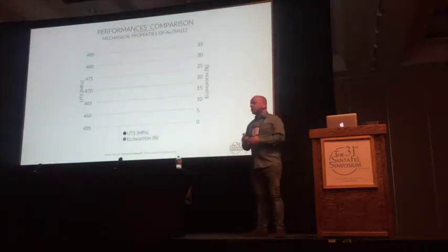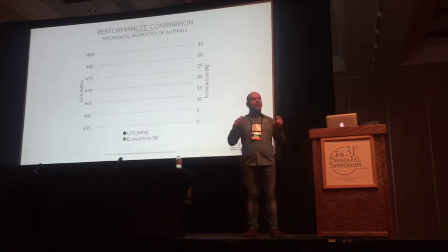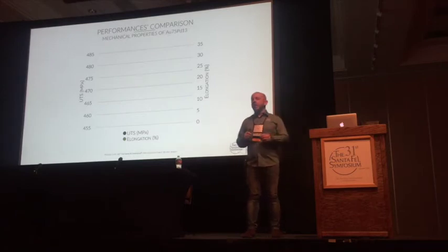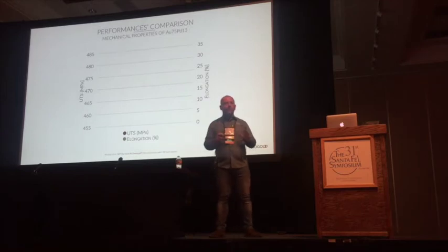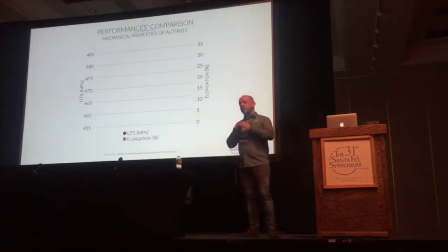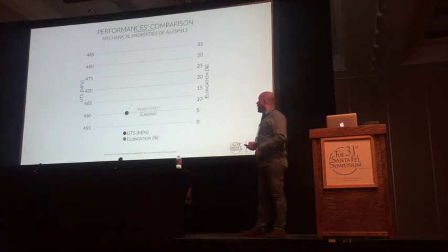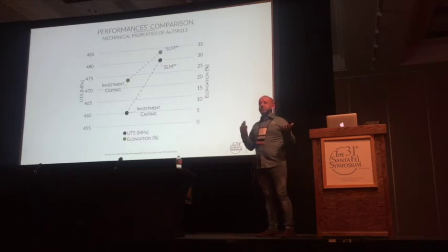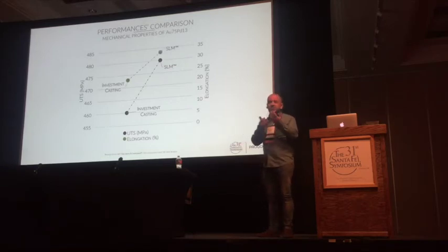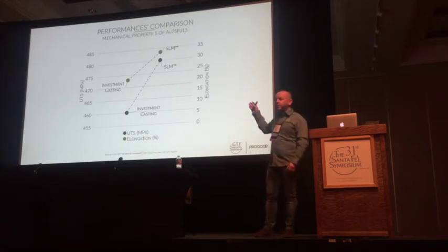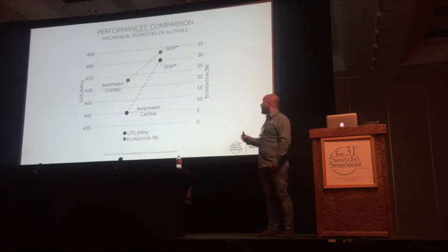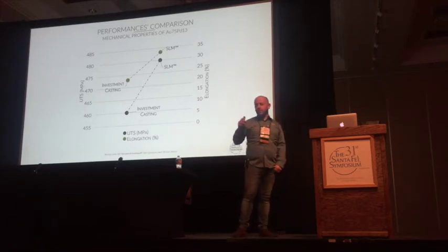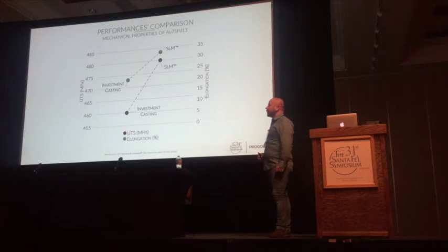About mechanical properties, I put this in because very often people ask me which are the mechanical properties, if they are the same as casting, and whether sintering is the same as casting in terms of mechanical properties. I would love to stress that this is not sintering. It's really melting. The only thing in common with sintering is the powder, but the process is totally different. In terms of mechanical properties, I do see a reason to go to 3D metal printing, because we have a tensile strength which is a bit higher. It could be the case of the white gold palladium that we were testing this year. And elongation is a bit higher. It could depend on how much finer and more defect-free the 3D metal printing structure is.